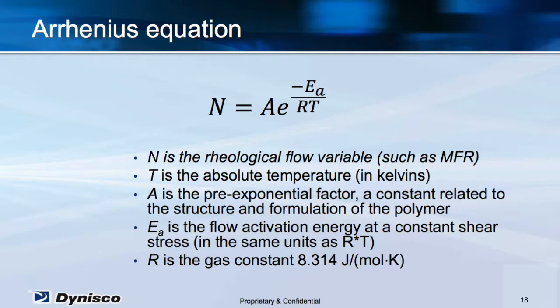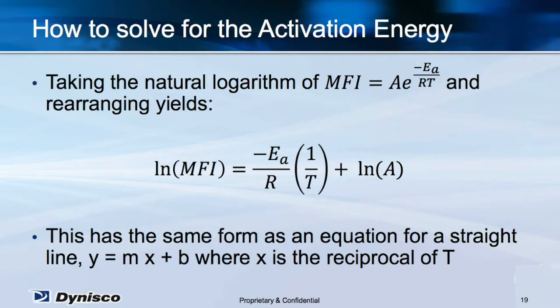The key point for us to use this relationship is to determine the so-called activation energy for the material at the shear stress we're running the MFI test at. The way to use this is to take the natural logarithm of the equation on the previous slide and recognize that you can rearrange it in the same form as the equation of a line, y equals mx plus b, where y is the natural logarithm of MFI and x is the reciprocal of temperature. The slope of this line is related to the activation energy, as you can see from the formula.